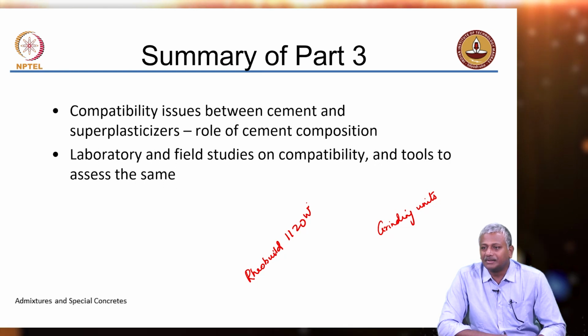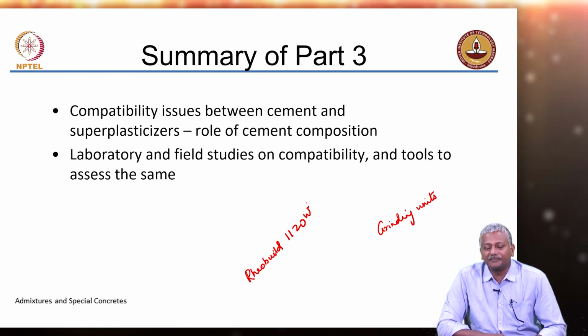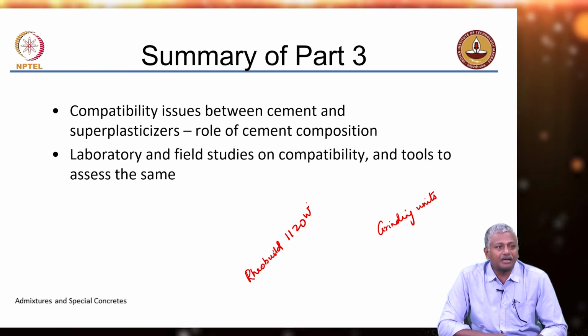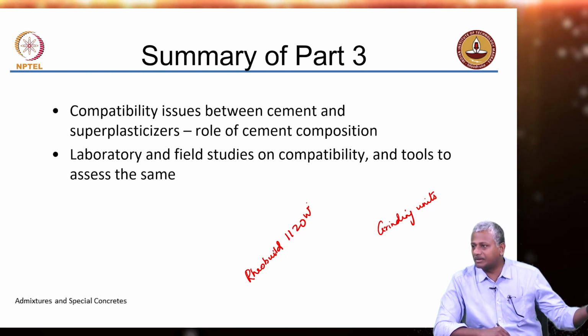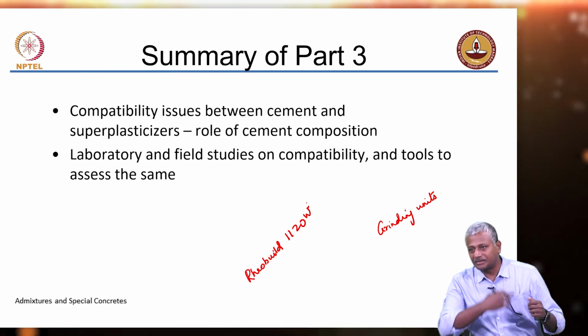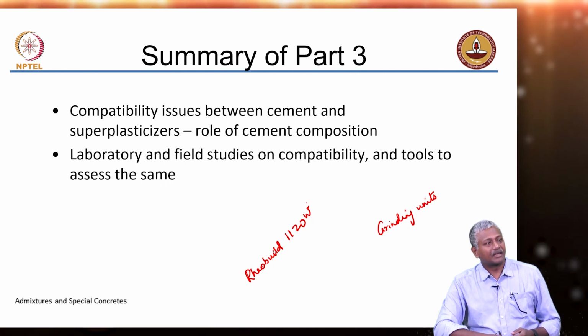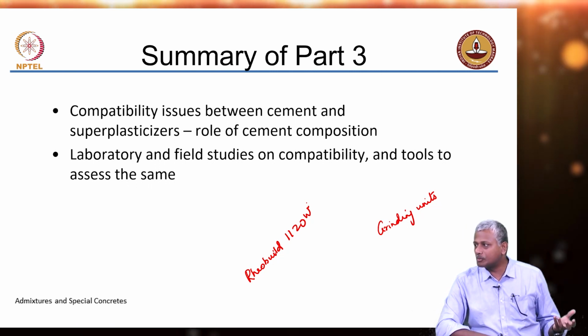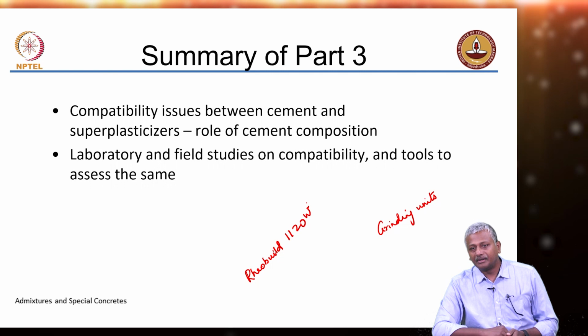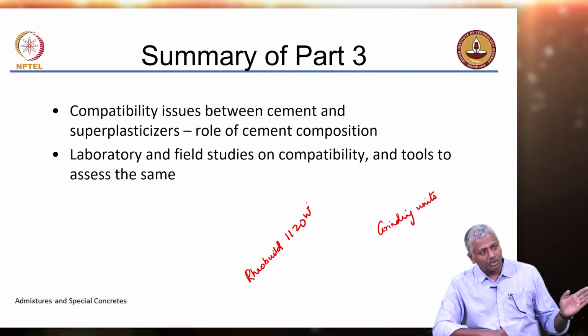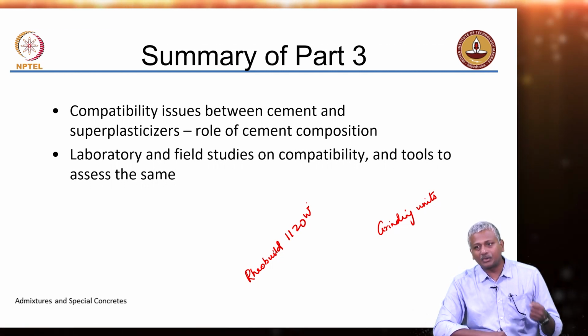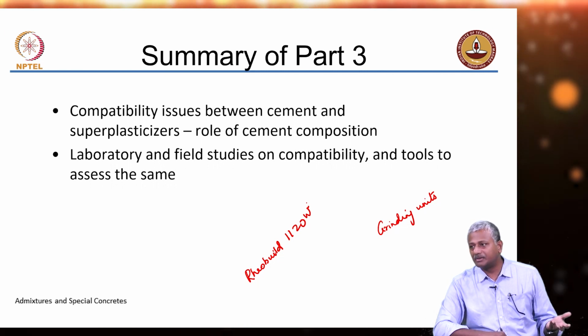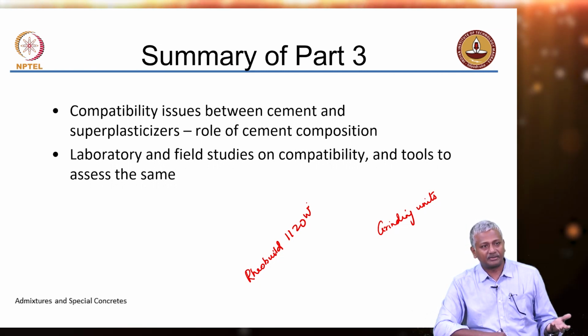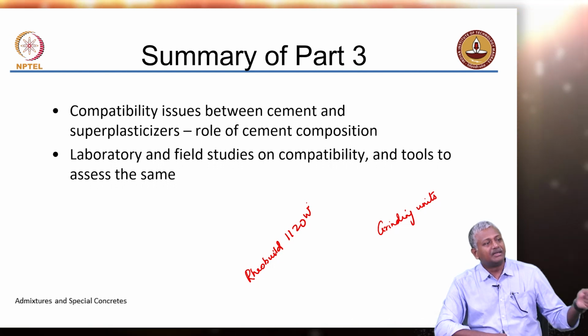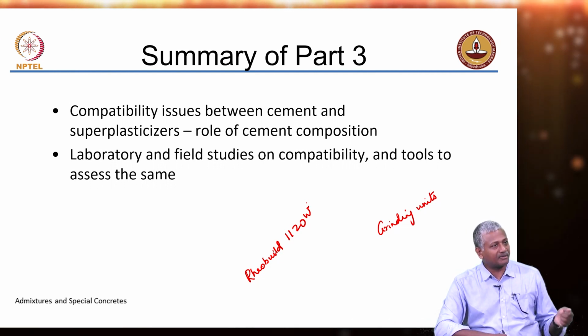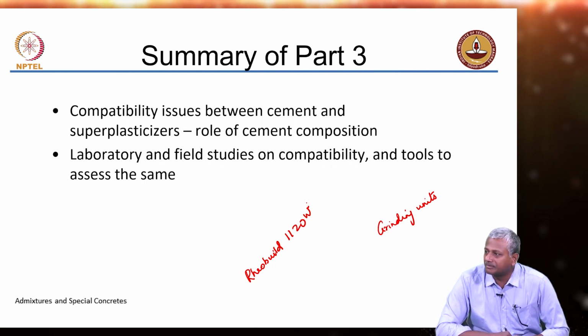In this site, they were not at all prepared. They came with a tilting drum mixer, that RM 500 or whatever, the one they can move around on the site, no? The tilting drum type mixer. That mixer, which could mix about 0.5 cubic meter, in the first 4 or 5 batches of mixing could never achieve the level of workability that was required. But by the 6th or the 7th batch, they had worked out how long they need to mix to really get the system to be effective.